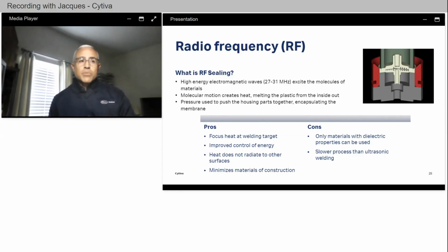Successful product and process designing with the use of RF incorporates the following. Ensure the membrane is enclosed between the plastic components. Consider longer seal times at lower energy levels for better control of the sealing process. And design the mold to minimize electrical arcing. Just like with ultrasonic, we recommend that you consult with the RF welding machine manufacturer to assist you in determining the optimal equipment, tooling, and parameters to meet your desired outcome.